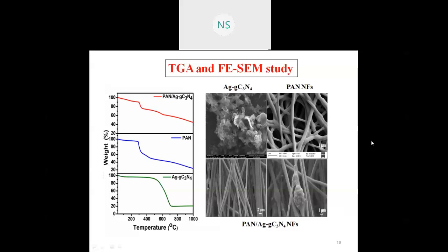This is the thermal stability as well as morphology study for that material. Obviously, because of the decoration of the nanomaterial over the surface of the polyacrylonitrile nanofiber, the thermal stability shows an abrupt enhancement. In the FESEM image, the silver grafted C3N4 shows some petal or plate-like structures. Somewhere it shows dots of silver over the surface of the graphitized carbon nitride nanomaterial.